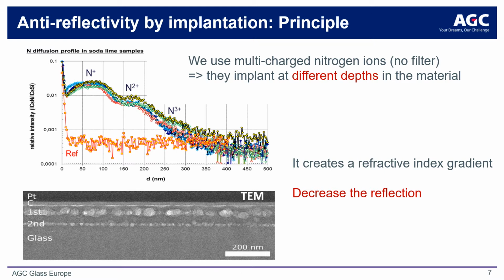Anti-reflective surfaces can be produced using ion implantation by creating a refractive index gradient from the glass surface down to the maximum ion penetration depth, in this case about 500 nanometers. Multi-charged nitrogen ions can be selectively implanted into the glass surface to various depths in order to create the appropriate index gradient. This ability to precisely manipulate the implantation of multi-charged nitrogen ions into the glass surface creates porosity, or bubbles, which locally affects the refractive index. In this manner, a highly engineered surface treatment can be designed.